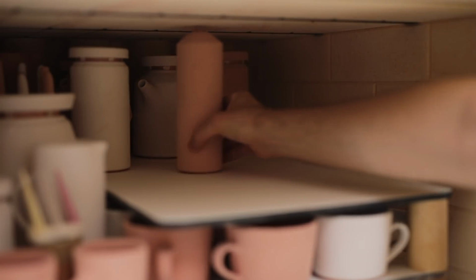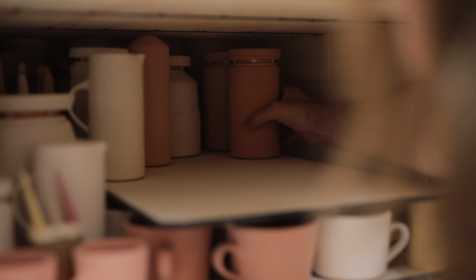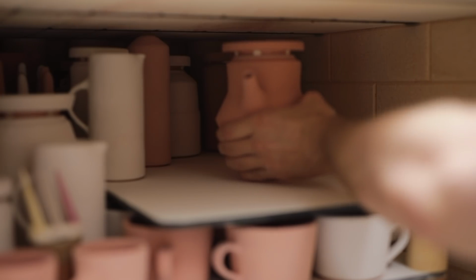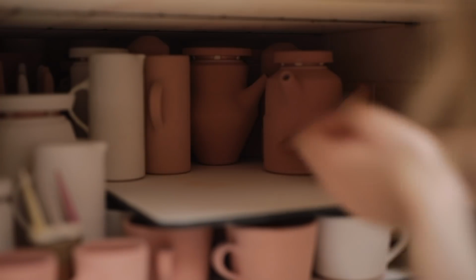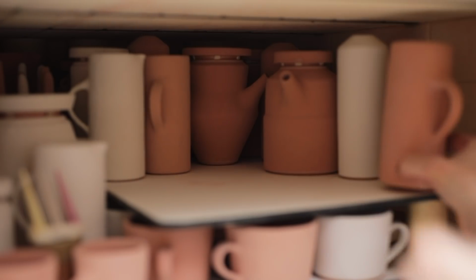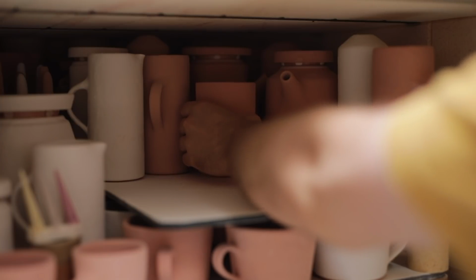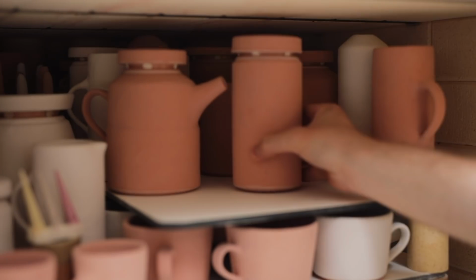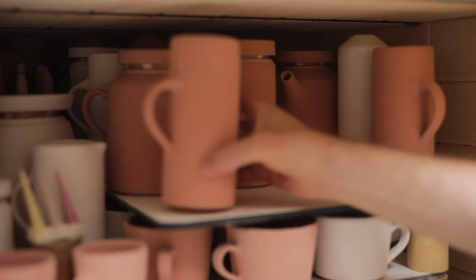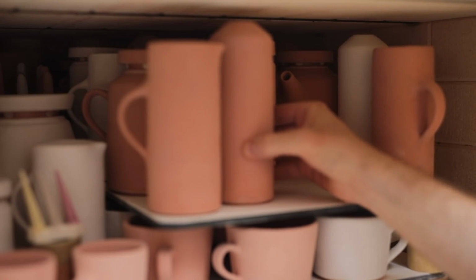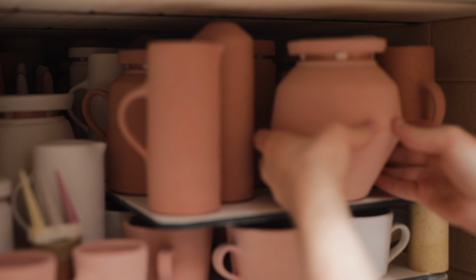For all the pots you see being loaded into the kiln, fundamentally, the glaze is the same base. The only thing that differs between them are single percentages of red iron oxide. The pink glaze contains just 1%, and the darker pink is 2%, and once exposed to a reduction atmosphere inside the kiln, this small percentage of iron will cause the glazes to turn green, whereas if they were fired in an oxidized atmosphere like you find in an electric kiln, these same pink glazes would fire to a sort of mottled yellow, which isn't particularly nice.